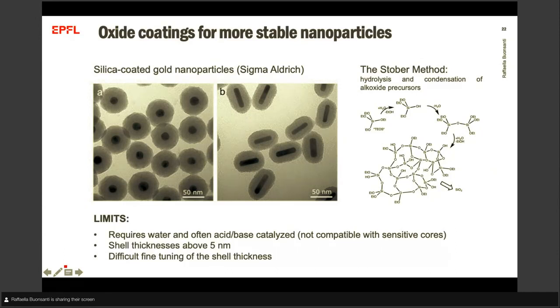Also, we have a shell thickness above 5 nanometers, and so we don't have a very tunable platform to understand when electron transfer and when energy transfer is occurring. It's also difficult to tune the shell because it relies on hydrolysis and condensation. It's not a layer-by-layer approach.